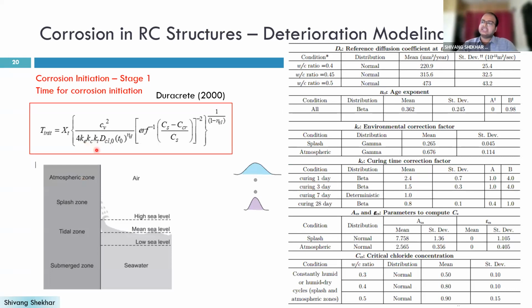Like what will be Ke, Kc, Kt, your diffusion coefficient, your surface chloride concentration, and critical chloride concentration, depending on the grade of concrete and the age of concrete. Now again, you can see in this table, and that's why I am saying that we should do a probabilistic assessment, because there is no fixed number. For each thing, they have given a mean and a standard deviation. Basically, they have given a distribution, a normal or gamma distribution, for different parameters.